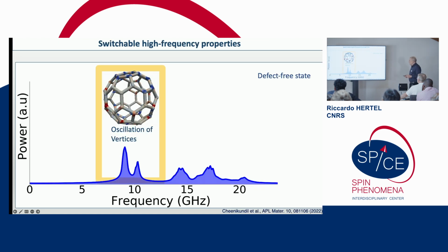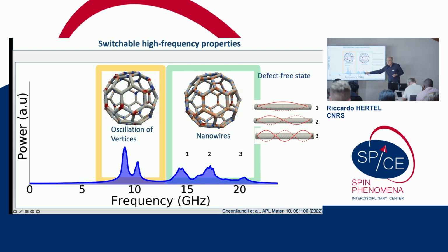And so now we can look at how the high frequency oscillation of this structure behaves. We expose this sample to a short field pulse, and thereby excite some ringing of the magnetization. And there are some pronounced peaks which are localized at the vertices, but that's not all. At higher frequencies, we have 3 rather distinct peaks, which, and this is strongly simplified, can be ascribed to a first, second, and third order oscillation within the wires. So these are modes that are localized within the wires.